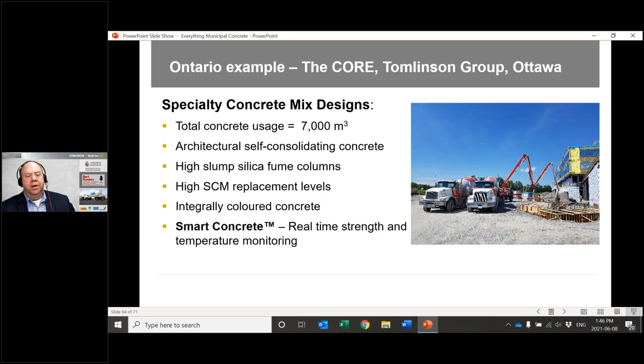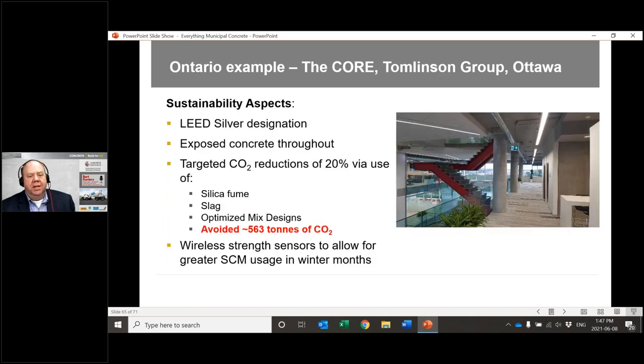So again, they're building a building during cold weather, winter months. They want to use, instead of the generic, as soon as it gets cold, we take all the supplementary cementing materials out. They looked at if we measure the actual temperature of the concrete and we calculate the maturity of the concrete in the field, let's see how much SCMs we can still use in cold weather months.